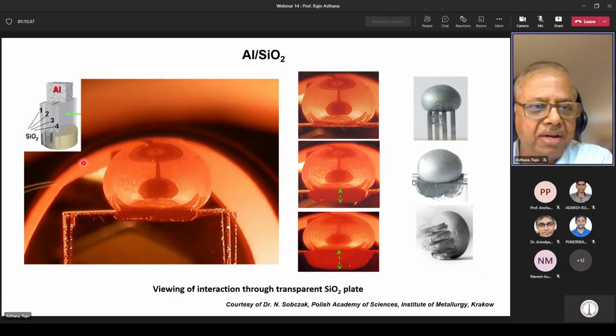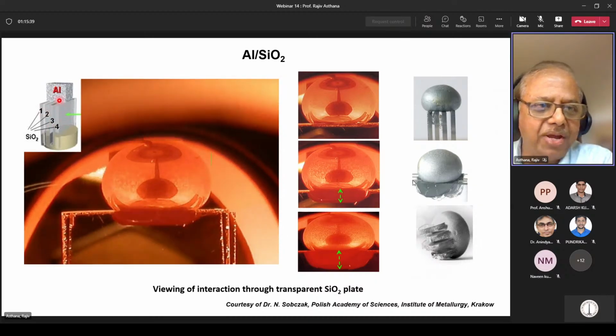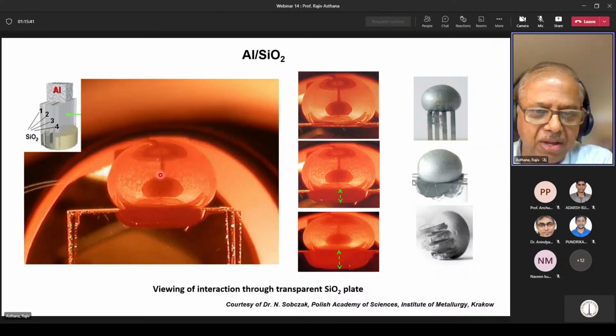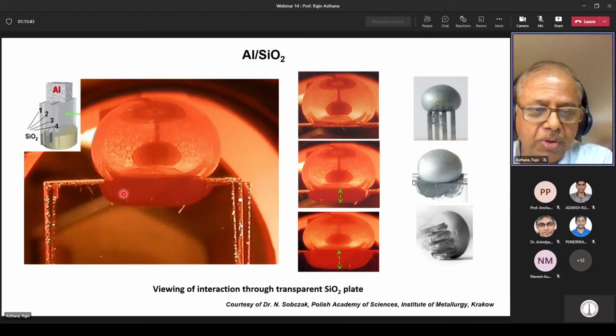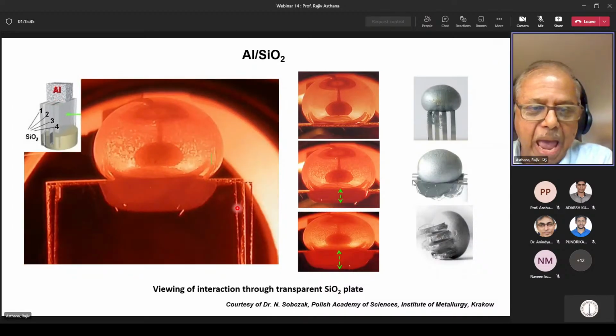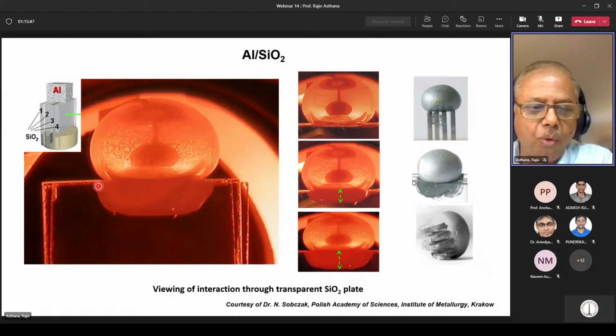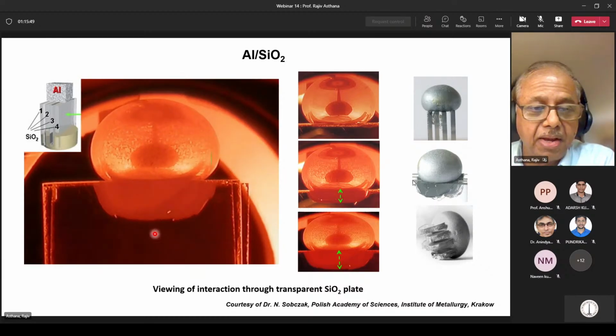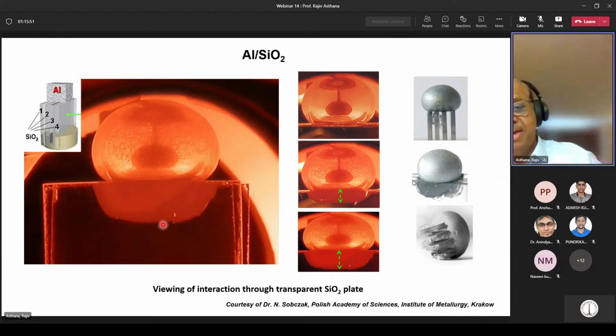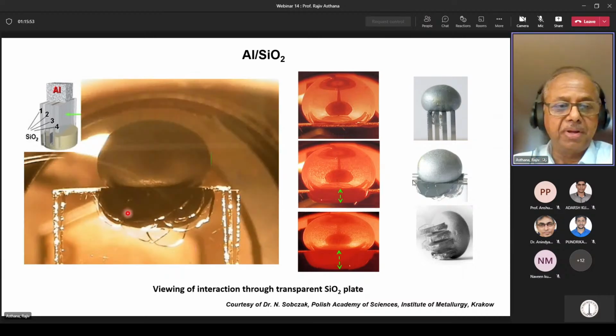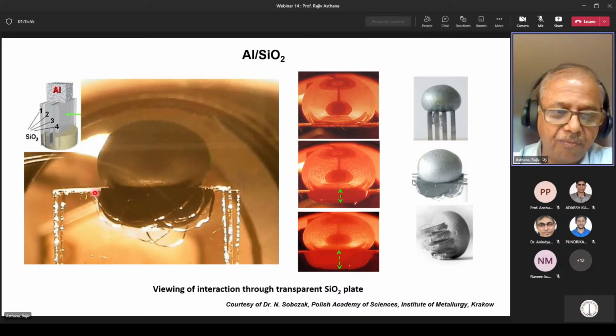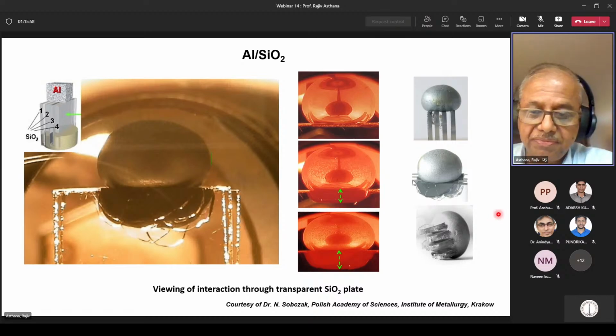The same thing is being done with multiple silica plates where you had aluminum on the top. So you're melting aluminum and allowing it to infiltrate the gaps between these quartz plates, and you can actually see the liquid propagating and how the reaction layer is forming. And after cooling, obviously, you form some quench cracks.